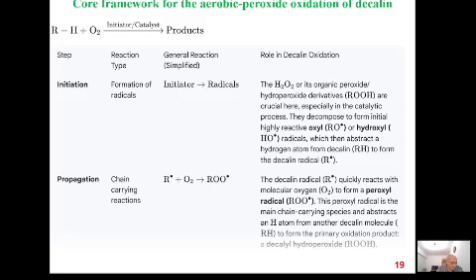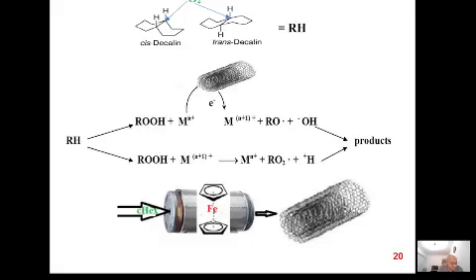The catalyst, typically a transition metal salt embedded and enrolled by multi-walled carbon nanotubes, dramatically changes the mechanism, participating in the decomposition of the peroxide through the redox cycle. The catalyst activates the peroxide to efficiently generate radicals, which accelerates the initiation and propagation steps of the oxidation.